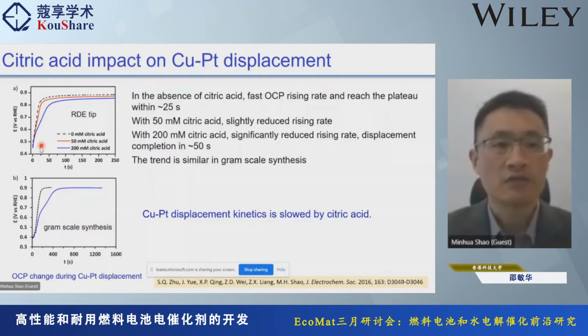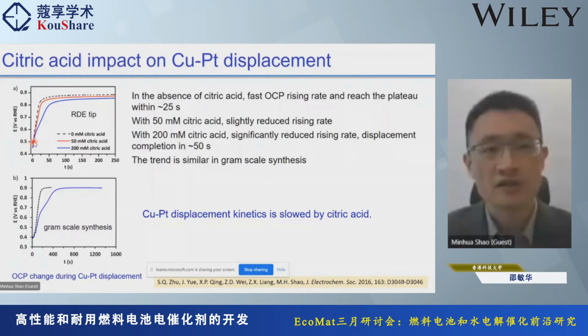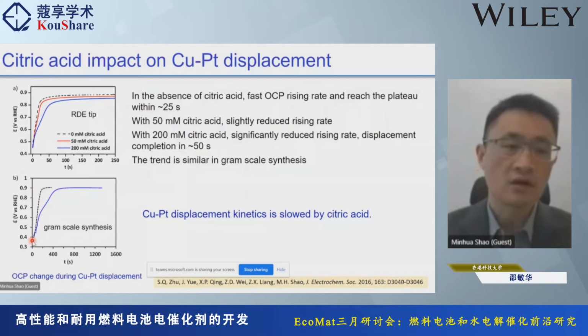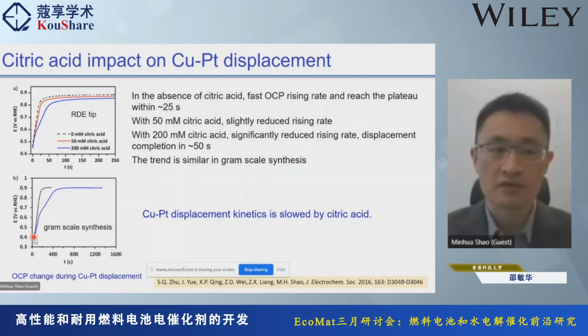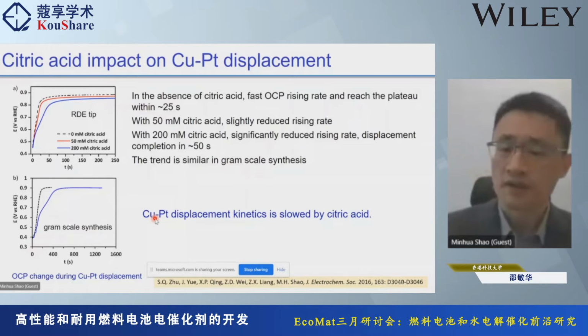Okay, and if you add 200 millimole of citric acid, you can see the blue line. So this process is significantly delayed. That means the citric acid actually reduced the reaction rate. And we can do this on a gram scale. The similar thing happened. Without citric acid, this process finished in 200 seconds. With citric acid, it's basically delayed until like 500 seconds.